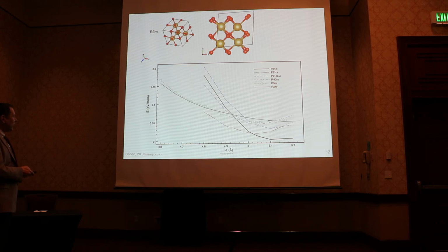So this is just showing energy versus strain. These are epitaxially strained calculations with fixed A and B axes on a surface. And the ground state, as everybody else has found, is monoclinic. And as everybody else has pointed out, under compressive epitaxial strain, you can stabilize this polar orthorhombic structure. The thing that I did that's different than everybody else is I ignored the nonpolar phase, so it looks like I'm getting the right result. So if you don't worry about the nonpolar phase, you can show that epitaxial strain will stabilize the polar structure.